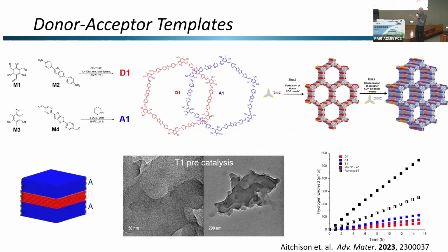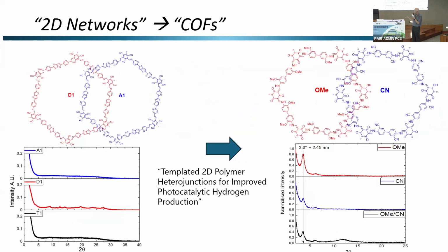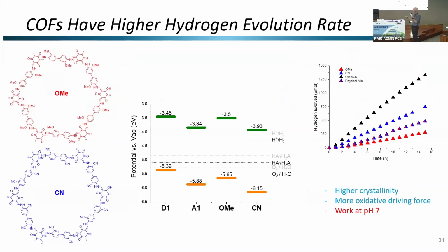When we published this paper, it wasn't rejected, but the reviewers didn't like the fact that we were calling this a COF, because if you want to really demonstrate that you've got a COF material, you have to show by X-ray a really strong reflection due to long periodicity. So this was what we call a 2D network type material. But eventually we were able to make COFs with this type of structure. These are the first materials, the ones that we published. We actually haven't published this one, but you see there are no really strong reflections. Here we see a very strong reflection that matches exactly the internal diameter of our structure. So we've definitely got a COF in this case. And they have higher hydrogen evolution, as you'd expect, than the 2D structures.